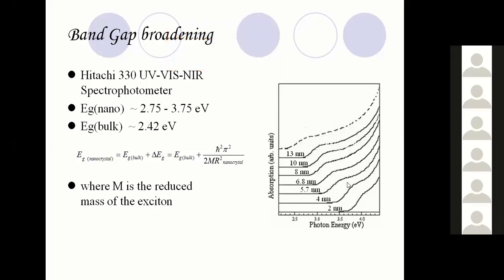We were discussing that band gap broadening takes place on the nanoscale. So we performed an experiment with cadmium sulfide. The band gap of bulk cadmium sulfide is 2.42 electron volts. But it has been seen that when the size of the nanoparticles changed from 13 nanometers to 2 nanometers, the band gap went on broadening. This is the UV visible absorption spectra. It has been seen that there is a blue shift in the absorption spectra.